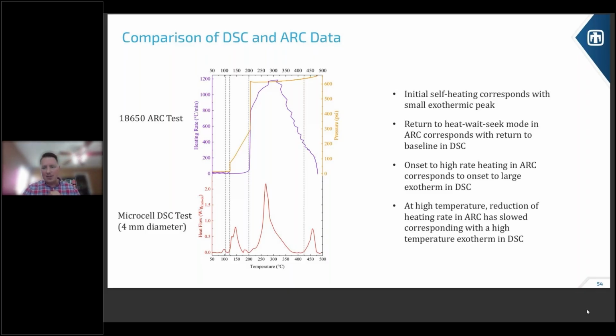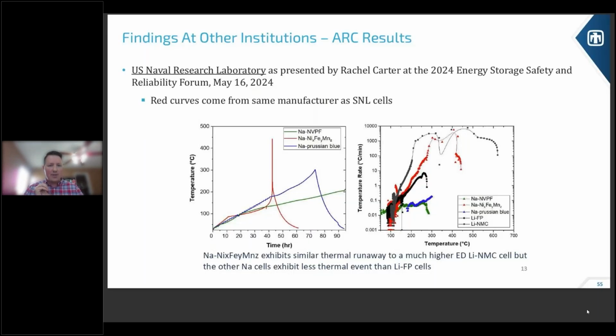Next. I think this is pretty much the end, so I have a couple things to point out. Actually, this is an important slide. Rachel Carter at U.S. Naval Research Labs has also done testing on sodium-ion batteries. The red curve, this is ARC, similar to what I showed you before. The red curve is the same cells that we had at Sandia. And her results on this ARC testing correlate very well with our results. We're seeing the same things.